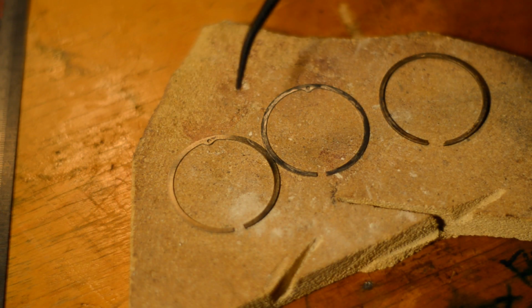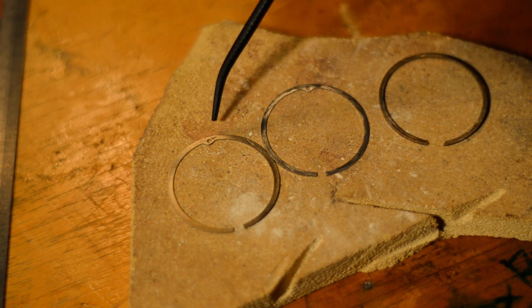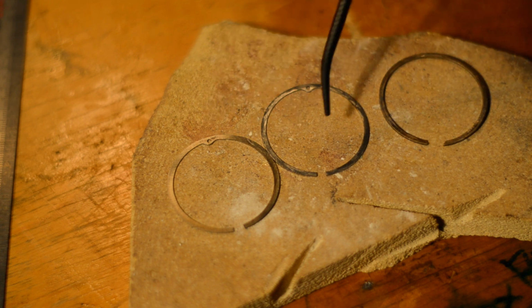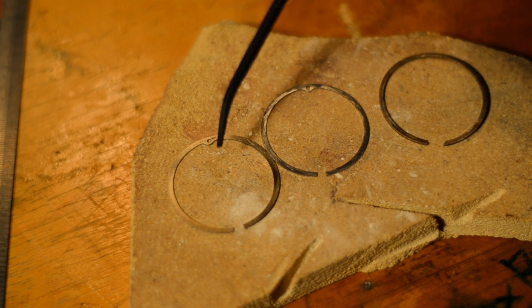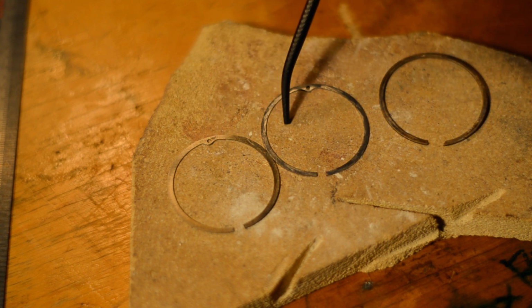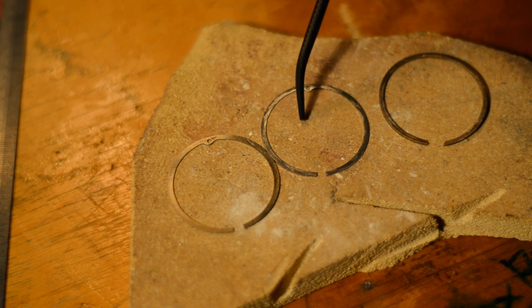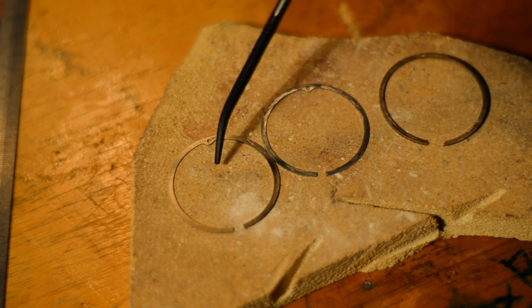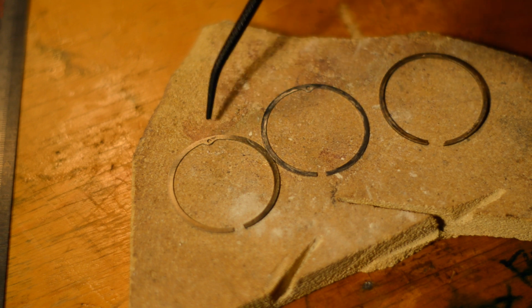The plating and heat treating failed, or actually I think the plating failed. Somehow it didn't stick to the metal. I'm pretty sure I cleaned it good enough. There might be too much chrome in this steel. I'm not quite sure what alloy it is. If you're watching this, Mark, maybe you could comment and tell me what alloy this ring steel is.